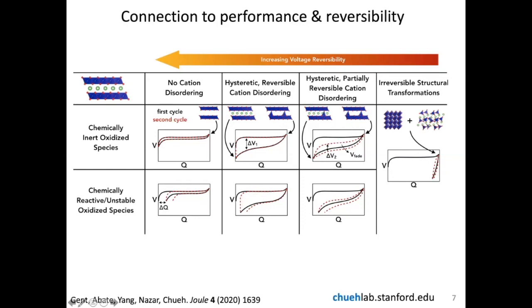so you have voltage fading. Then moving further to the left, you could have a situation where the transition metal can move around freely, going back and forth between the lithium and metal layer. So you still have the large hysteresis, but there's very negligible voltage fading in the material. And then finally, there could be a situation where the transition metals don't move at all. Right now we are in the third column with the lithium rich material. We have some ability to move the metals around to accommodate the stabilization of the high valence state, but the hysteresis is large and you're losing material, losing oxygen over time. The most optimal situation will be the first column here, where you have no cation disordering. At first, this seems really good, but the problem is if the transition metals are not moving around, then you lose the stabilization mechanism of undercoordinating the transition metal.